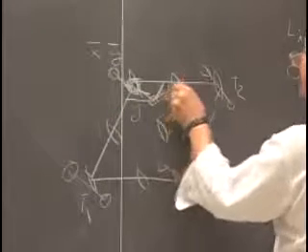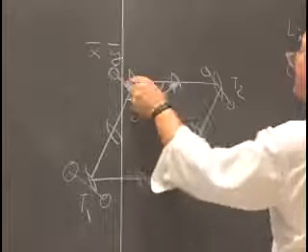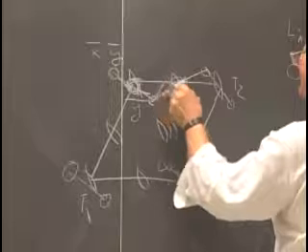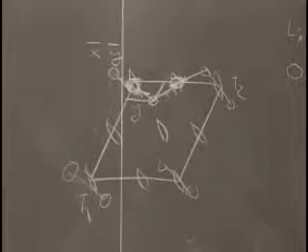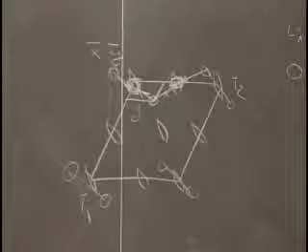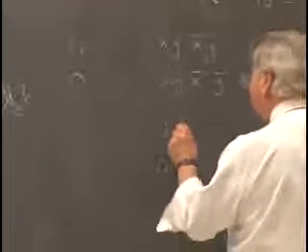If I let x and y migrate to 0, 1/2, this atom will join together with this atom, and I would get just one atom sitting there. So there is a position also of the form 0, 1/2, and a position 1/2, 0, and a position 1/2, 1/2 that are the location of these 4 distinct twofold axes.